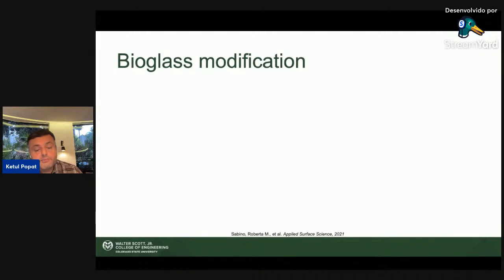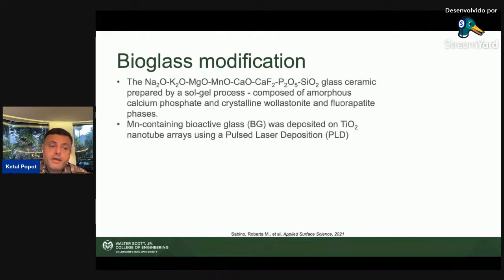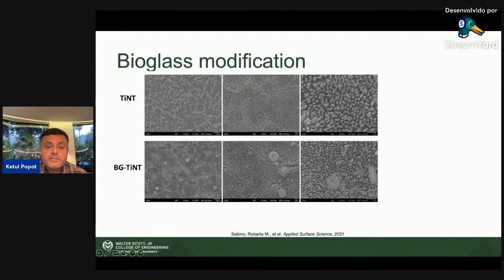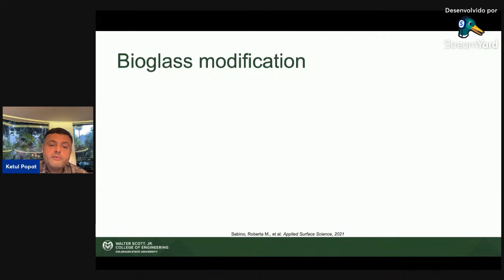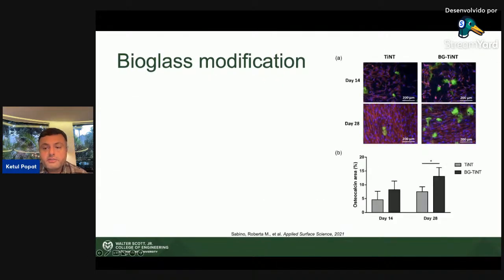We've also done some bioglass modification. This is in collaboration with Dr. Giulietta Rao from Italy. They deposit bioglass on these nanotube surfaces. These bioglasses have manganese. Manganese has some activity. And what we find is that we can still maintain the structure of the surfaces, but when we start doing the cells, we find that even better differentiation of cells is happening.